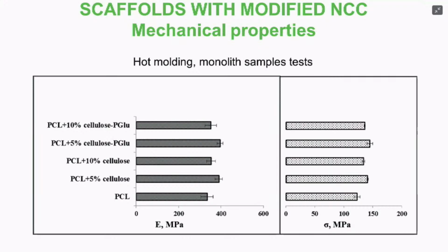and that is a plus for us because we wanted not only to increase the mechanical properties of the material with nanocrystalline cellulose, but the main aim of this work was to introduce biological functionality. So here we could say that our composites did not give a great increase in mechanical properties. However, they stay almost on the same level as pure polycaprolactone. So they could be used for further experiments.